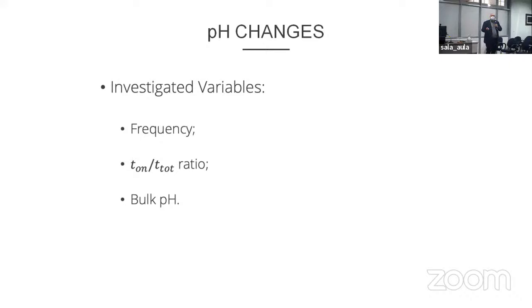Then we start to investigate what we can do to inhibit this pH change. Let me tell you, the problem with the pH change is that you develop a new material for acidic solution, but really you are working at the interface in alkaline pH values. And then your electrode just leaks into the solution.